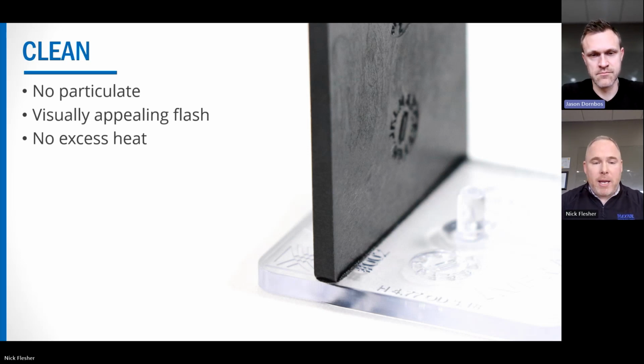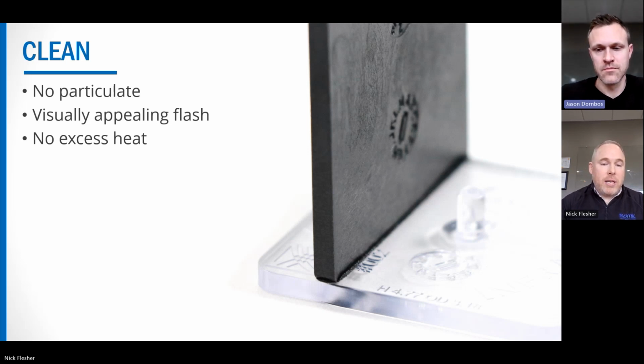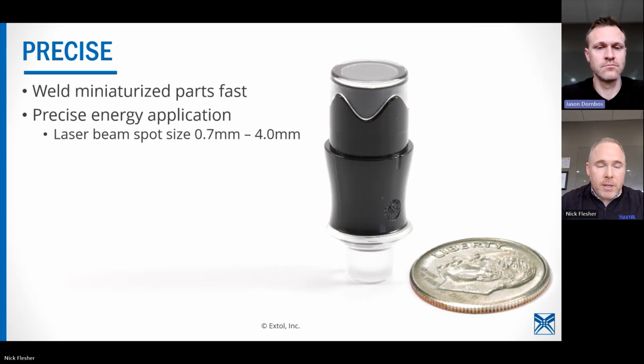We've shown some examples already. This is actually about a 1.5 inch plaque. It's not our best image, but I think it does show really well. The flash is essentially nothing. There's always flash, but it's oftentimes visually appealing. It's like a purposeful melt is what I would say. You don't get any excess heat. In this particular example, you can see there's really not much heat affected zone past that little small roll of flash. So clean is number one.